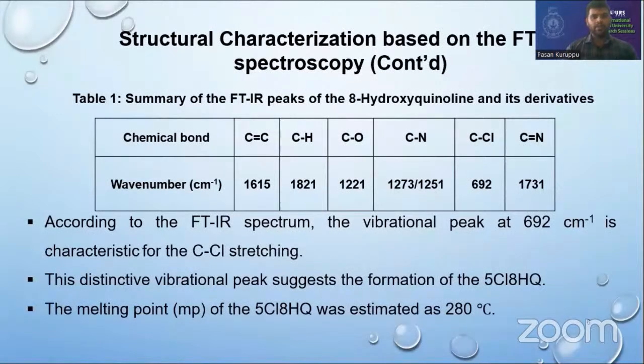So, according to the FTIR spectrum, the vibrational peak at 692 is characteristic of carbon-chlorine stretching. This distinctive vibrational peak suggests the formation of 5-chloro-8-hydroxyquinoline, since all of the other chemical bonds are also available in 8-hydroxyquinoline as well as 5-chloro-8-hydroxyquinoline. And the melting point of 5-chloro-8-hydroxyquinoline was estimated as 280 Celsius.